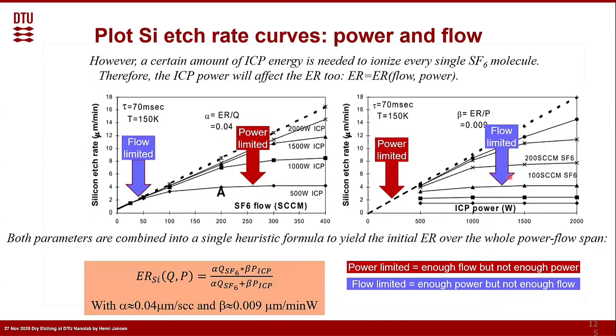And now we make a plot. What we do is we're going to really check experimental. We look at the silicon etch rate in micrometers per minute. And here we change the SF6 flow inside the plasma for certain fixed values of ICP power. What you see is that at the lower flows, it still goes up almost linear with flow, but then after a while it starts to saturate and it becomes fixed.